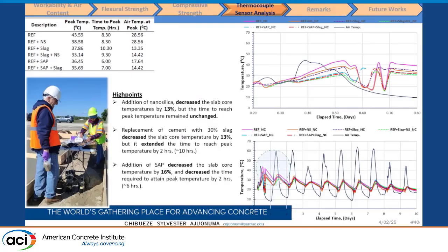And we also tried to evaluate the temperature gradient for the thermocouples that were instrumented in the slabs. For that, we noticed the addition of 30% slag replacement reduced the core temperature from almost 44 degrees Celsius to 37 degrees Celsius. And even the addition of SAP further reduced the core temperature, with the addition of SAP and slag.